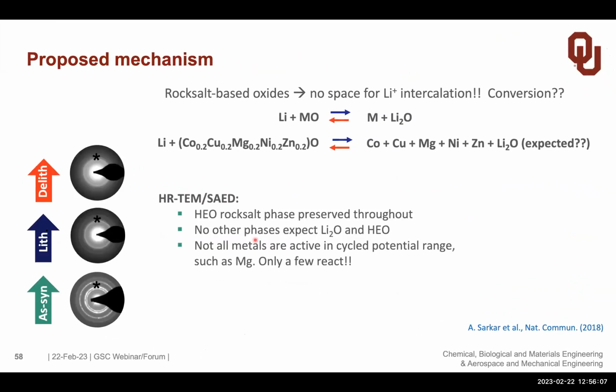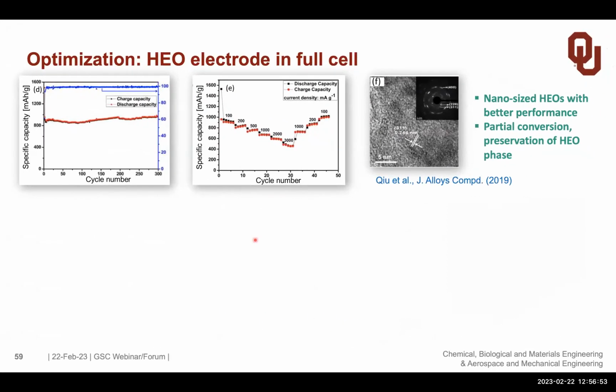And we have some ideas on how that works, but let me try to briefly mention it. We have studied that by detailed electron microscopy and X-ray studies. We do not incorporate all the cations in the electrochemical conversion of the material. Some of them are not participating in the electrochemical reaction, but they provide a stable rock salt structure in the entire process. This way, the system has kind of a memory of that structure, and it will cycle back and forth between lithiated and delithiated structure. So this is what we have proposed, and other people have also confirmed that.